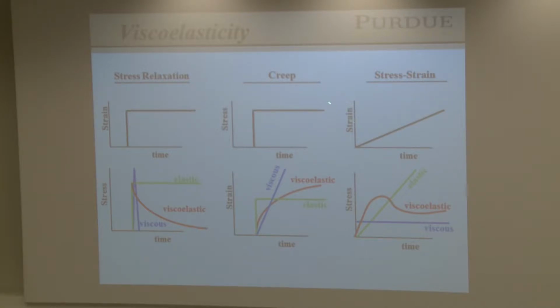And here's another one, which is what we call a stress-strain curve. In this case, the strain is linearly increased with time. For an elastic material, the stress will track the strain, and it linearly increases with time. For a viscous material, it'll be constant, because the strain rate is constant, and the stress is proportional to the strain rate, and the intercept of this line would be the viscosity. A viscoelastic material, especially a polymer one, shows this really interesting behavior where it increases linearly for a while, then all of a sudden it bends over, comes back. I mean, it's really an unusual response. And the challenge of our group is to try to figure out how we model this viscoelastic response in nonlinear deformation experiments. And these are important in terms of application.